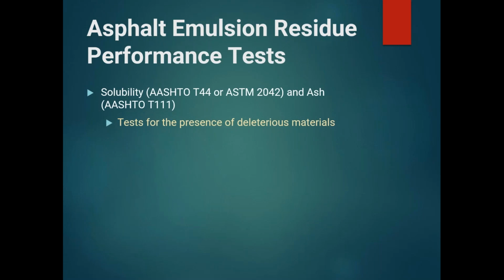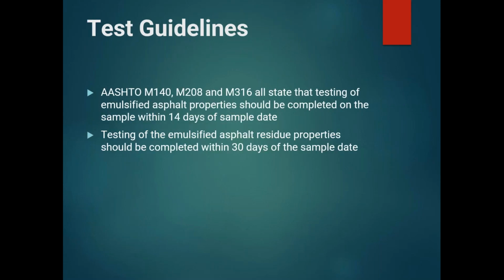Solubility and ash, both of these tests are used to test for the presence of deleterious materials in the residue. AASHTO M140, M208, and M316 are all emulsion specifications for the anionic, cationic, and polymer modified emulsions. And all of these state that testing of the emulsified asphalt properties should be completed on the sample within 14 days of sample date. That's one of the reasons that it's important that as soon as that emulsion is sampled, it's sent in to the lab on the day it's pulled, because the clock starts ticking on that day.